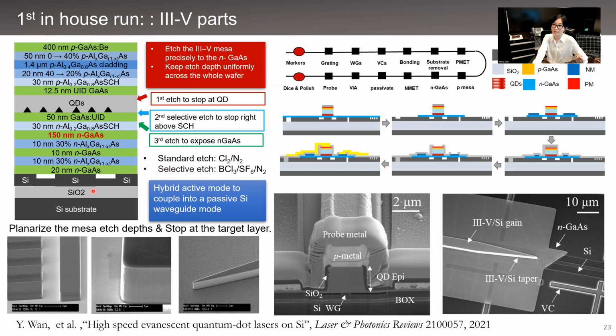So to precisely control the mesa etching depth, the quantum dot gain mesa was defined in 3 steps. So the first etching step was controlled using a laser monitor to stop around 100 nanometer above the SCH layer using chlorine-based ICP plasma etching. And afterwards, a short selective dry etching comprising of BCl3, SF6, and N2 gases was performed, where we have a high etching selectivity of GaAs over AlGaAs to ensure that the whole wafer can be uniformly exposed down to the 30 nanometer SCH layer. And finally, we do a timed short etch to remove the 30 nanometer SCH layer and just expose the 150 nanometer N-GaAs contact layer.